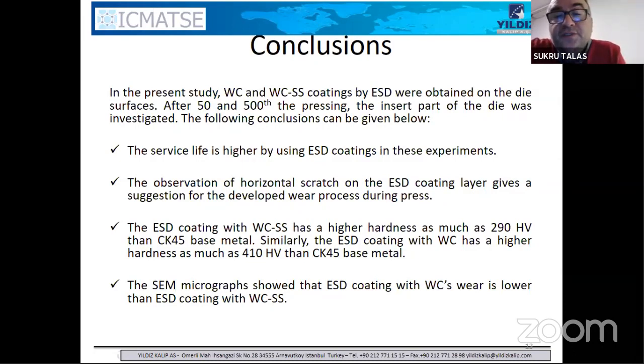The observation of horizontal scratches suggests that tungsten carbide is better than tungsten carbide plus stainless steel, because it increases the surface hardness of the steel, especially in specifically designed areas. We can get an advantage in wear rate, especially with tungsten carbide compared to tungsten carbide plus stainless steel.